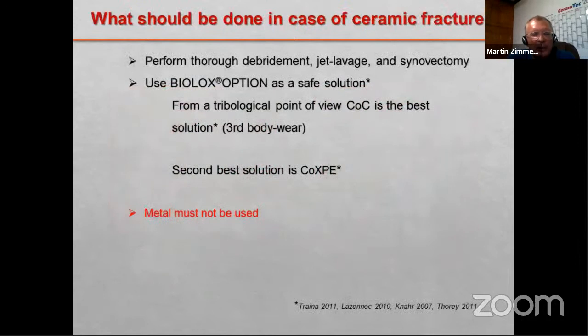Why and what should be done in case of a ceramic fracture and exchange? First of all, you have to perform a thorough debridement, jet lavage, and synovectomy, because it is actually impossible to get rid of all the ceramic particles. Most of them you can see - they are large enough. If you do the synovectomy, you take a lot away, but there are a lot of microscopic particles which will still remain inside the articulation.